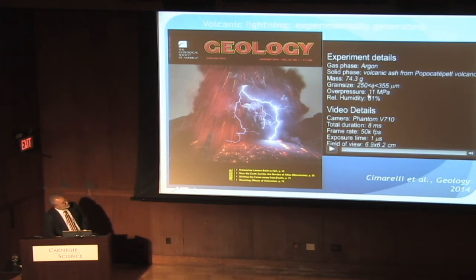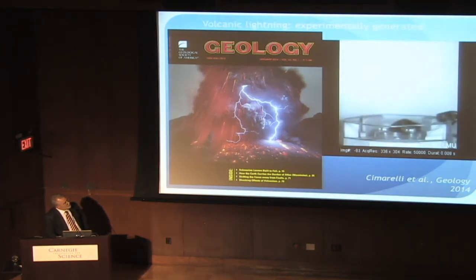Look on the right, and here we go. We had a problem with our video with these eruptions. We had flashouts in certain frames. And so when we were about to give up on everything, somebody said, let's speed it up by a factor of 10. And then it came. Now, I have no time to go into the details of what we think is going on here. There are basically two factors going on: a triboelectric effect, friction, as you can well imagine, probably jumps right into your mind. And then you have to get the field gradient set up so that the fine particles, which are differently charged from the large particles, will effectively discharge in this manner.